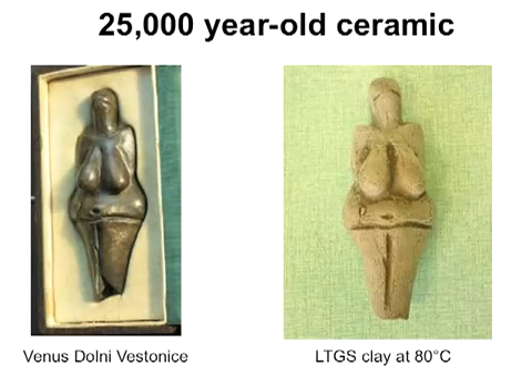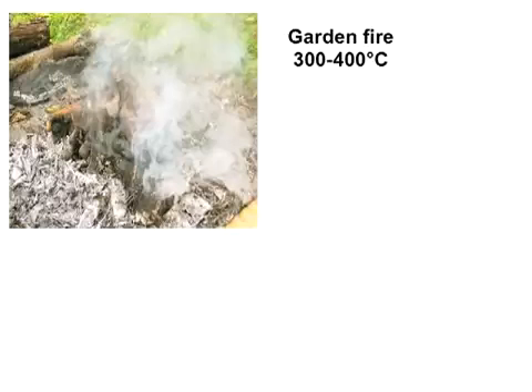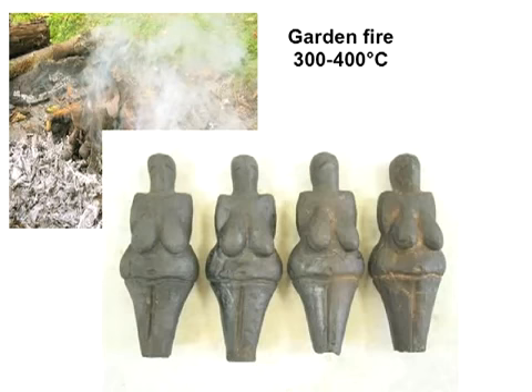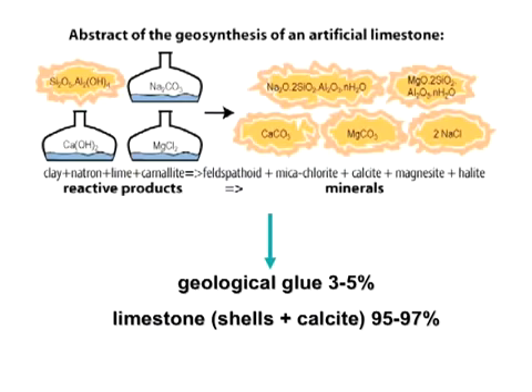Well, very easy. We have replicated it, dried at 80 degrees C, put it in a garden fire in a reduced atmosphere, 300 to 400 degrees C, and we got our Venus. This is how it has been done, provided the chemistry is in place, and the chemistry is very easy to achieve with ashes, with clays, with salts that are commonly found in clays, and so forth. You find other information in the book Geopolymer. Thank you very much for your attention.